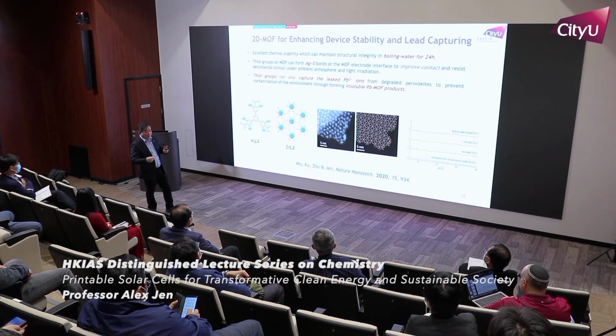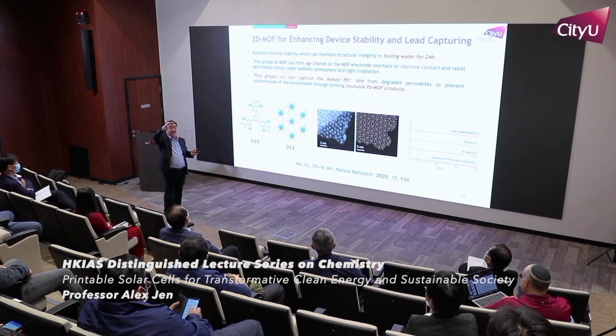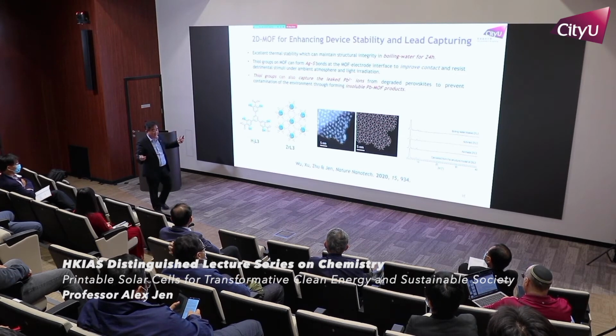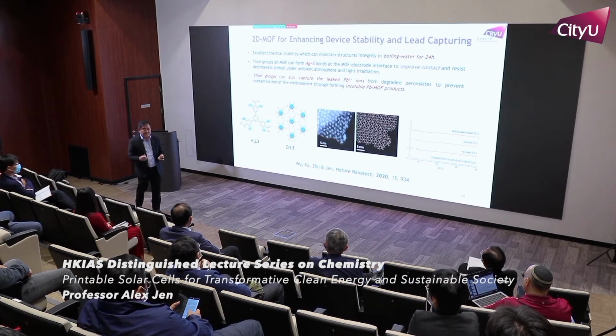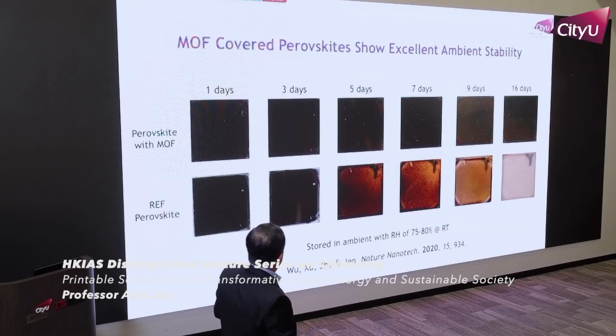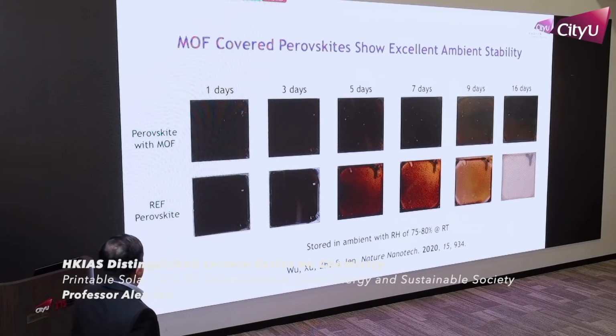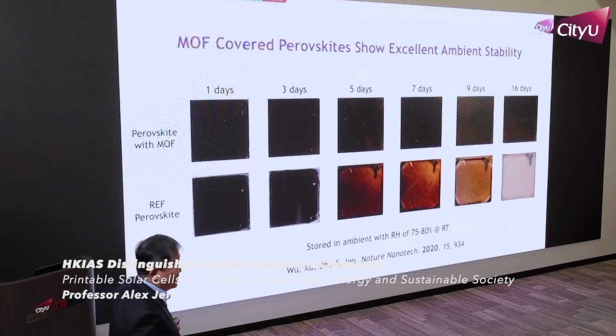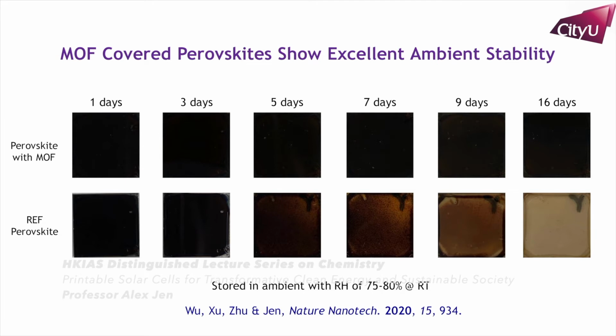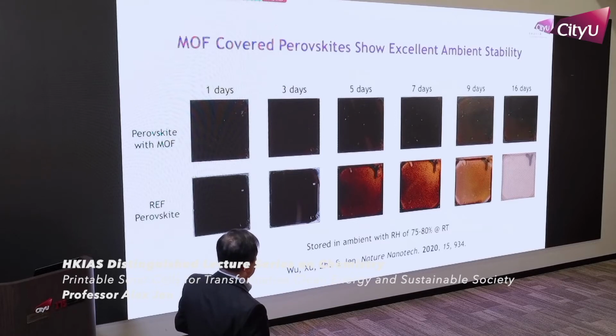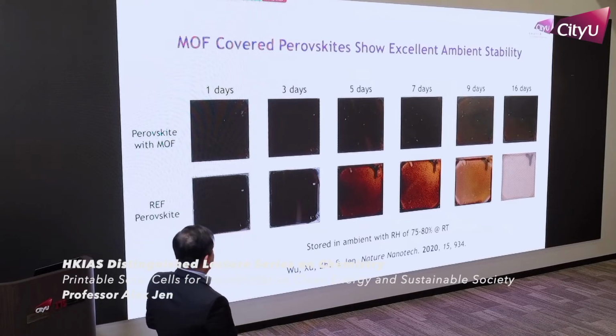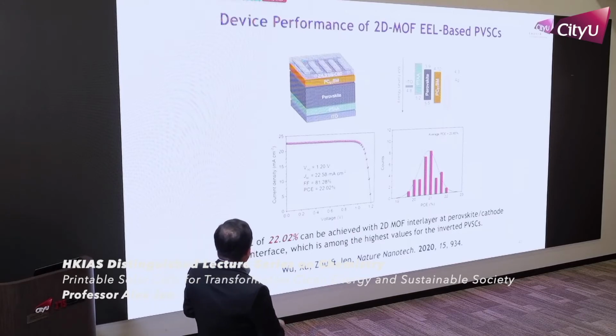And SH can also react with the top electrode. If I use it on the top as a transporting layer, SH will react with silver to form a silver sulfide bond. So with all these potential reactions, you can take advantage of that. We coated it on top of a perovskite and exposed the perovskite to the very humid Hong Kong environment. Over many days, if you don't have this coating, the perovskite reacts with moisture and tends to decompose relatively easily.